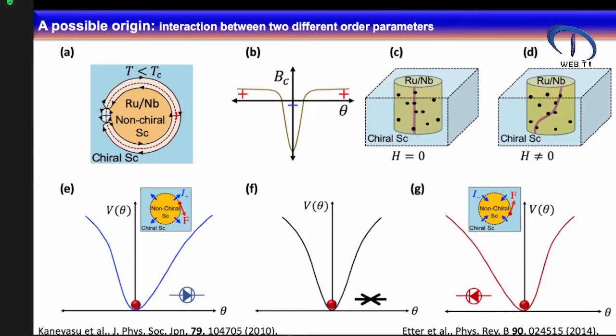And this frustration develops a superconducting vortex state. You can understand the vortex state with this simple graph. Theta along the x-axis means the direction around this ruthenium inclusion, around this normal superconductor, and the B-axis is the magnetic field. You see that this magnetic field goes negative, diverges, and then here it is positive. So this is actually a vortex.